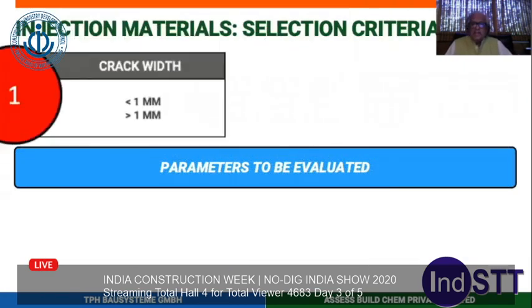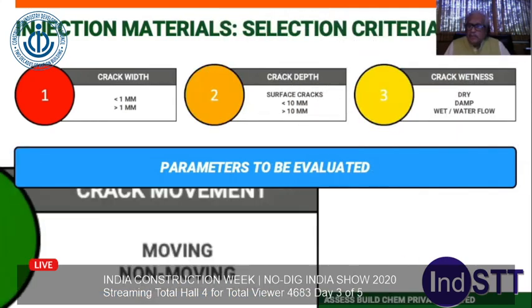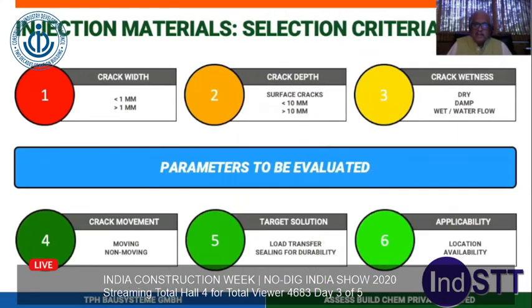So a large gamut of materials are available, but these are to be selected depending upon very few important things, which is the crack width, because crack width will determine the viscosity. Crack depth will also determine the viscosity, how deep you want the material to penetrate. It will totally depend upon whether the crack is dry or damp or whether water is coming out of it. If the water is coming out of the crack, you have to really stop that water incoming by putting a pressure with your machines to push back that water and the injection resin to reach the place where it is designed to reach.